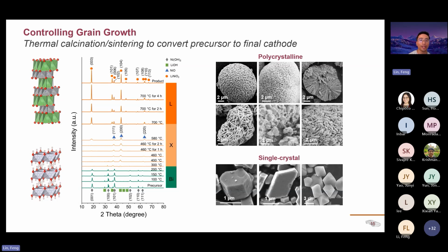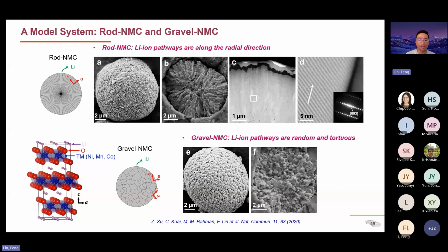To do this type of study, we take the precursor material, which is usually a metal hydroxide, such as nickel, manganese, cobalt hydroxide, then mix it with lithium hydroxide precursor and heat it up to different temperatures and monitor the phase transformation behavior, to investigate at what point the layered phase starts to form and at what point we can finish the crystal growth to obtain the final product. By doing all these diffraction studies, we get indications on how to control the temperature profile. This is one example of that type of study, which was published more than 5 years ago.